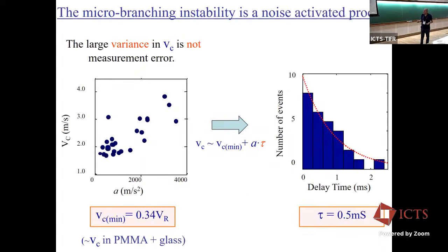And what we found was that the critical velocity was an approximate linear function of the acceleration. Now you might say, okay, there's a lot of scatter here. These are dirty experiments. I have no dirty experiments in my laboratory. Actually, there's no noise, or the noise in these experiments is the size of the dots. What this scatter is telling us something about the physics of the problem.